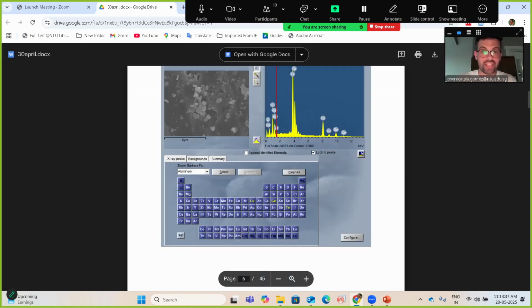You have copper telluride there. I can see it. Yeah, there is copper telluride, which is fine. An impurity phase is fine. It's completely fine, man. You're okay. But that could be the reason why your peaks move. Again, you've made a phase and it's clearly the majority because your Rietveld refinement is extremely good there too.